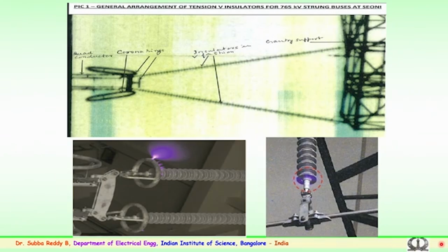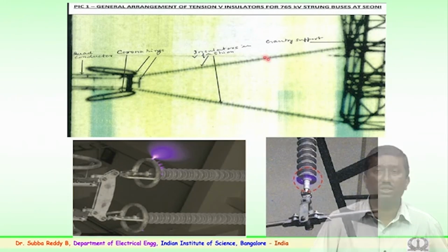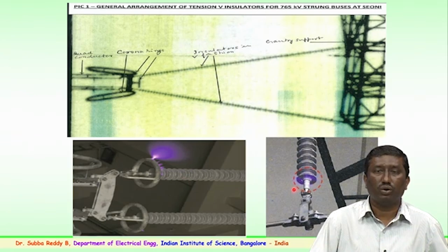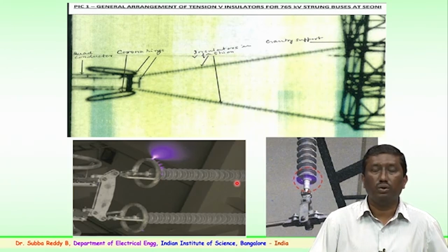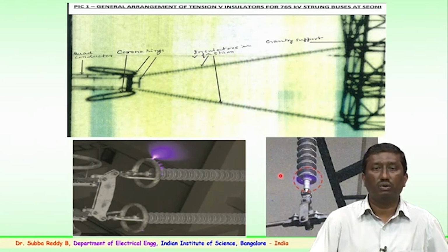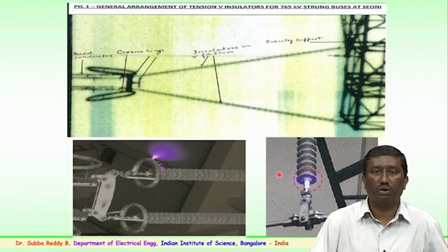So, how is corona important, and why does it degrade the surface? As you see here, the corona comes from the hardware, here from the corona control rings. The corona which is generated, the discharges which are continuous, are likely to damage the sheds, as they continuously impinge on the surface of the insulator. Over a period of time, the surface of the polymer insulator, which is supposed to be hydrophobic, loses its properties, and the surface degrades and could lead to the failure of the insulation.